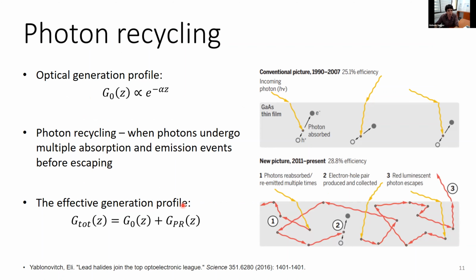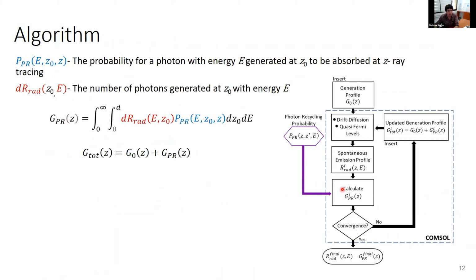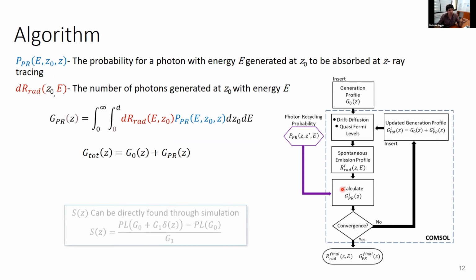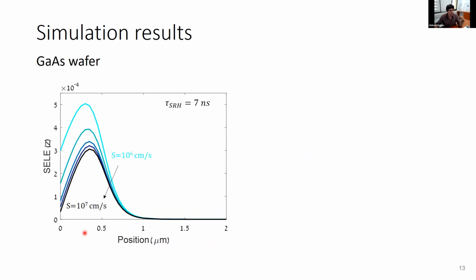This is quite a mess, and we do this with an iterative process between coupling several simulators. But the nice thing about it is that with the simulator, we can actually calculate the spatial external luminescence efficiency directly, assuming specific optical generation profiles. So we can assume, for example, a surface recombination velocity and see how this will affect the SLE that we can extract. And this is what we see here.